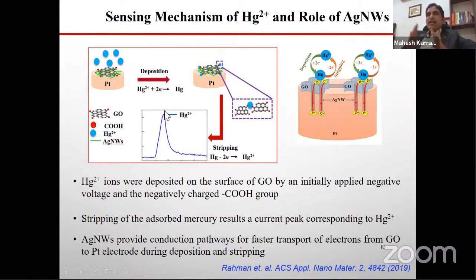We can measure at a particular voltage how the current is changing, and this current is proportional to the available mercury ions. We are using silver nanowires here because there is charge transfer between electrode and electrolyte, and we want it from graphene oxide to the electrode. Charge transport should be faster, so we can use these metal electrodes.